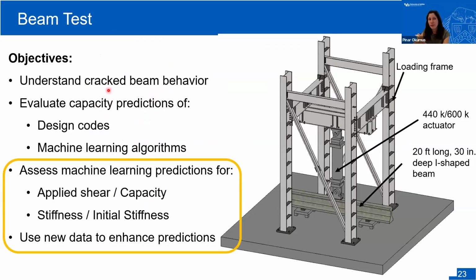Okay, so that's what we learned from the cracked beam test. I think the most important thing we learned was that even though your beam is cracked, you may see cracks in the field, but your capacity will still be a couple of times above the design code predictions. So the second thing we did with our test data is that we tested our machine learning predictions for the applied shear and stiffness. And then we also used some of the new data to see if we could enhance our predictions.